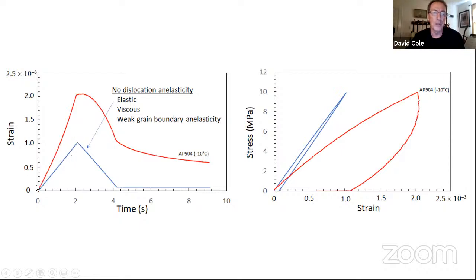But no dislocations. So in terms of strain over time, your deformation would follow in phase according to the modulus and how much viscous straining occurs with applied load. There's no out of phase component. You can see you would very much miss the behavior. You could say, all right, let's try a lower modulus to get the slope up, but you'd never capture the time-dependent piece of this behavior.